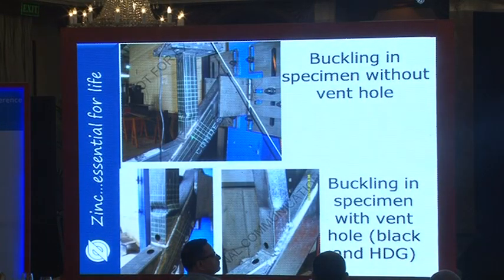But we then show the buckling. You can see actually the buckling in the samples here if you look carefully at the vertical beam there with the gridded positions on it to measure deformation. And we did this both with black and also hot-dip galvanized structures to determine the effects of galvanizing on the buckling loads for these K-joints with the vent holes in the usual places.